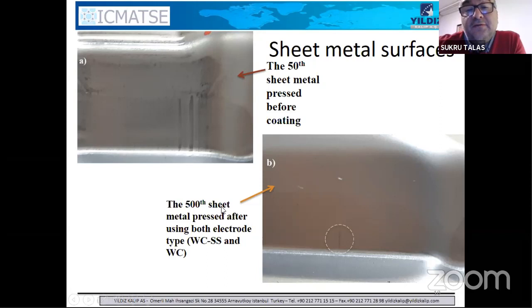After 500 sheet metal pressed after coating, you see there is only a very small scratch here, and the rest is very clear. It's extremely clear, and we were not expecting this. We were expecting maybe 100 or 150. We kept looking at it, and nothing happened. We were shocked. So it's a very good surface quality, and the company was also very happy with this result, because they could save thousands of dollars on die metal and sheet metal.